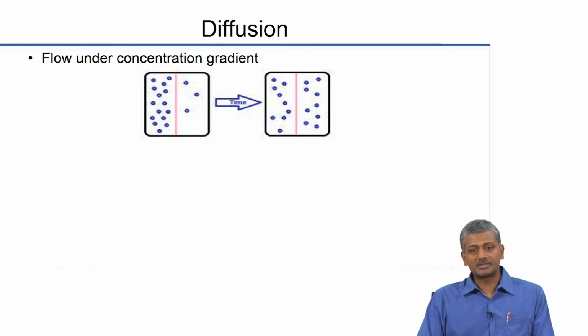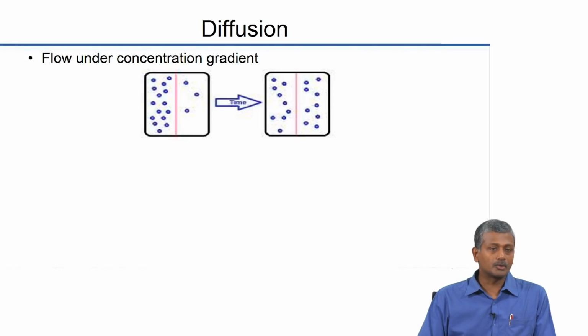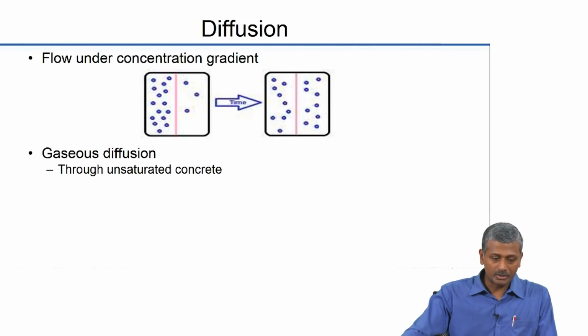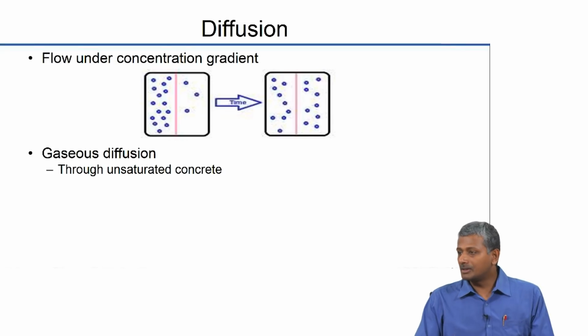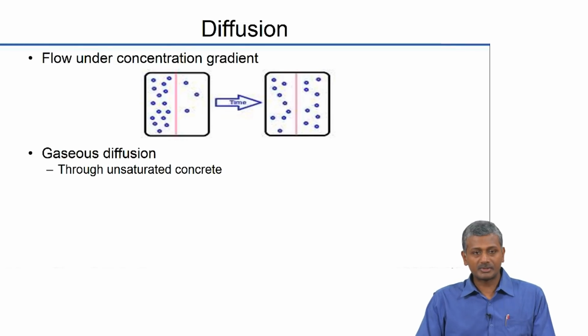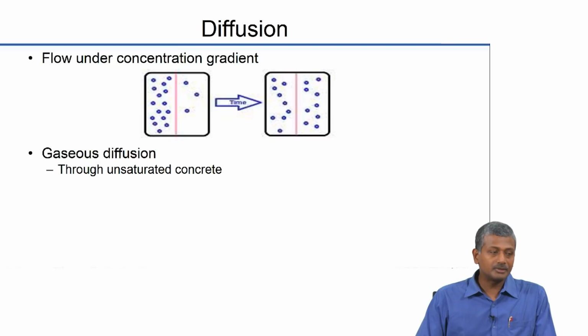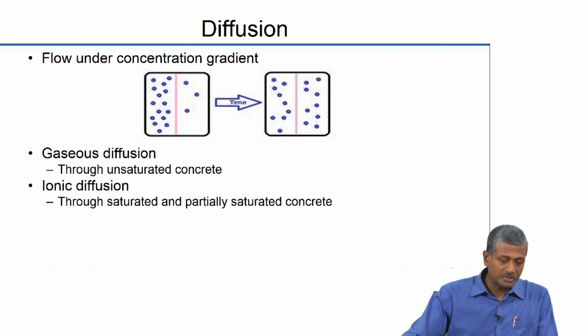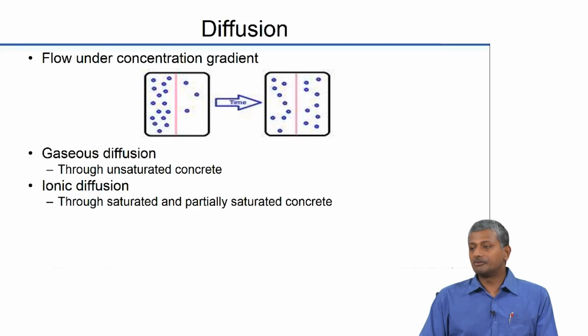So ionic species will tend to diffuse through semi-permeable barriers from locations of high concentration to locations of low concentration. And this will happen until there is some sort of an equilibrium reached in this process. When gases diffuse through concrete, they primarily need an unsaturated medium. That means they need very little moisture in the system, preferably no moisture for the gas to diffuse easily. Whereas when you have ionic species, they generally diffuse through saturated or partially saturated concrete.